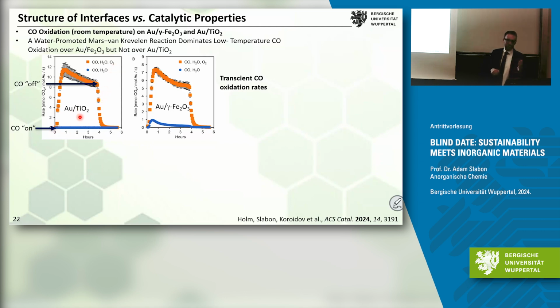With the catalyst gold and titanium, no CO2 is being formed. If you add oxygen, the CO2 kicks in and arrives. Now, if you do the same with iron oxide, we throw in the CO with water. What's this? We have an increase of CO2, but with no oxygen. If you insert oxygen, you have an even higher activity.